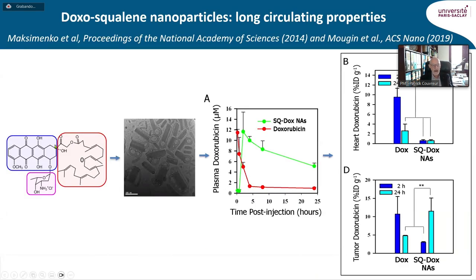As you can see here, we have linked the doxorubicin, which is a major anti-cancer compound, with the squalene. And after putting this bioconjugate into water, you can see that we obtained elongated nanoparticles with a size of around 100 nanometers. But what is very interesting is that after intravenous administration, those nanoparticles will provide much higher concentration of the squalene doxorubicin products as compared to what was obtained here in red after administration of the doxorubicin